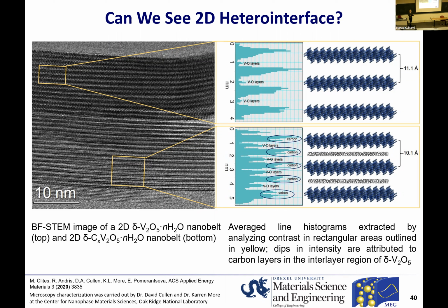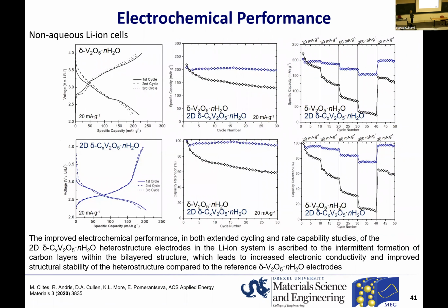So we interpreted this as formation of carbon layer. Now let's compare electrochemistry. On top, you have the reference material, which is just bilayered vanadium oxide. And at the bottom, it's what I call carbon pre-intercalated material, or material with an oxide-carbon heterointerface. The change in capacity retention is drastic.